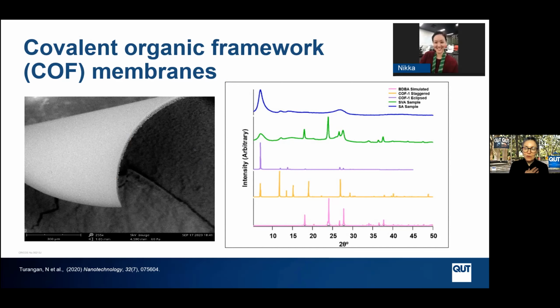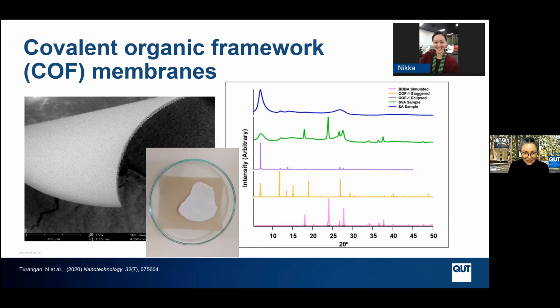We're able to measure the mechanical properties of these membranes using nanoindentation, which is kind of an information gap that's existed in COF studies for a while, because it is fairly difficult to synthesize them in a form which is amenable to these types of mechanical measurements. She's worked on scale up. There's no scale bar here, but I think this is a 4-inch watch glass that she's, apologies for the imperial, that she's synthesized this in. So you can see we're up to sort of tens of square centimeters of membrane size. It's a really interesting project to watch grow and develop.